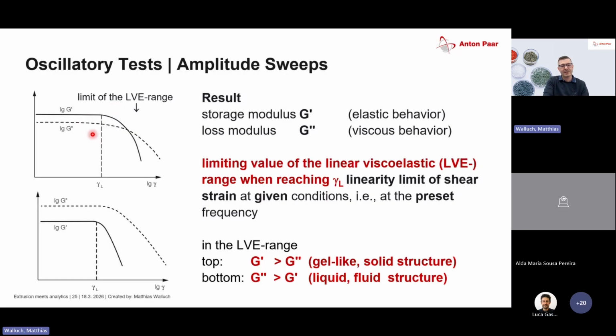And the second thing we see is G prime is higher than G double prime. And this means that G prime has more impact on the material behavior. So G prime is reflecting the elastic behavior. So the material is behaving more like a solid than like a liquid. If we have a look at the lower curves, it's vice versa. We have G double prime higher, G prime lower, and therefore the material is more liquid-like. So this would be easy flowing. This would be more or less like a gel or like a solid.